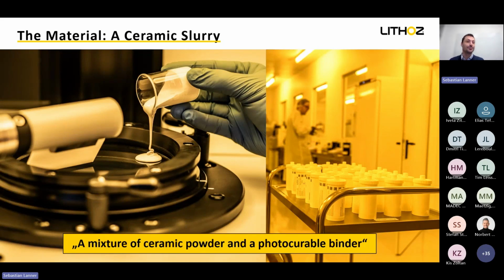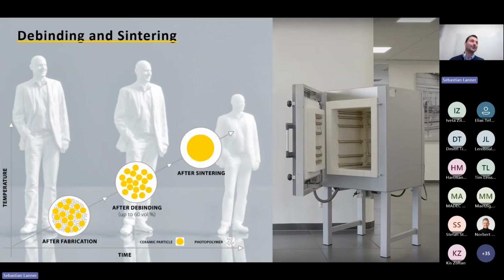So we have our 3D printed part, we have a cleaning step, and then we go to the important step of the thermal post-processing, debinding and sintering. You see here 3 figures of our CEO, Dr. Johannes Homa. Some of you maybe know him already. And the first figure on the left side shows him basically directly after the printing and cleaning. Here we see also in the small round image the gray polymer structure holding the yellow ceramic particles in place. And from here, the thermal post-processing journey begins.